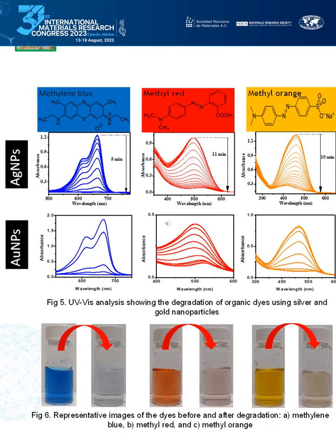The dyes used to evaluate the catalytic activity of the silver and gold nanoparticles were methylene blue, methyl orange, and methyl red. As can be seen, the degradation was carried out faster with the gold nanoparticles. For example, methyl orange took 10 minutes to degrade with silver nanoparticles, while gold nanoparticles only took 6 minutes. Moreover, in the last figure, it's possible to observe the disappearance of the color in the three dyes, which demonstrates the complete degradation of the methylene blue, methyl orange, and methyl red.